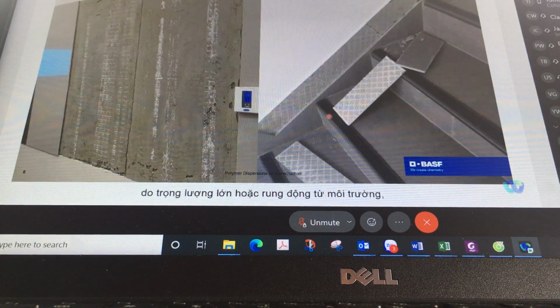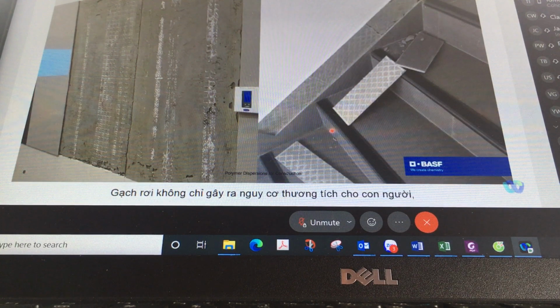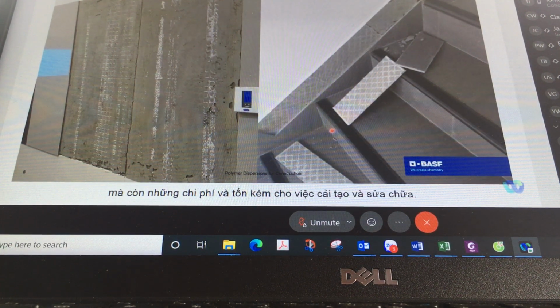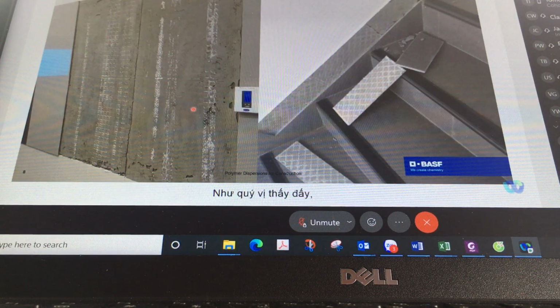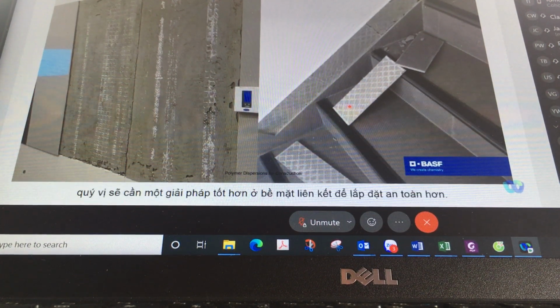Although properly installed, due to the weight of the tiles or the vibrations, tiles may fall down. Falling tiles not only present the danger of personal injuries, however, unexpected and additional costs will be needed in the subsequent renovation. As you see, the failure is happening at the bonding surface between the tiles and adhesives. This indicates you will need a better solution at the bonding surface for a secure installation.